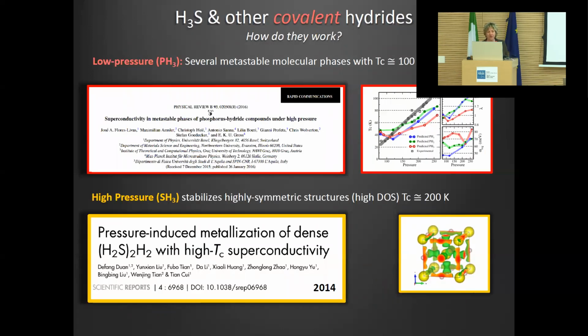So let's start from the compounds which form at the lowest pressure. And here we have an example. This is PH3. This is a compound where the Eremets group reported measurements of superconductivity. These are these squares in this plot, in 2015. The synthesis is similar to SH2, but it's done with phosphine. So the synthesis starts from phosphine. And the paper reports only the behavior of TC as a function of pressure. What I show here are calculations reported in this paper, which show that there are actually several PH compositions which match quite well the behavior of TC with pressure.